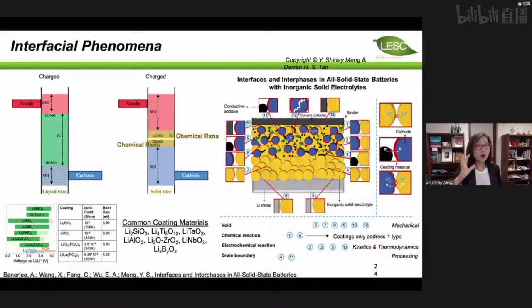Number three, the bigger problem for solid is that in the liquid cell, the liquid can flow freely. Whenever you have an empty space, the liquid will flow in. Now in the solid, if during the synthesis you have a void, an empty space, that's not good because you have created a lot of extra interface. So in this chemical review paper, we said you have at least 6 extra interfaces compared to the liquid electrochemical cells, because the void can also play a very important role.